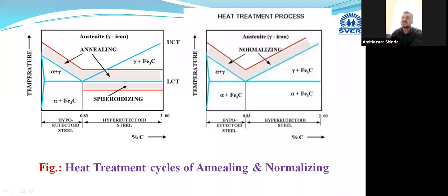And at this higher temperature zone, whichever grains of austenite are there will become coarse. Its size will become larger and larger, and whichever martensite we get at room temperature will be very brittle in nature. Hence, for conducting hardening, we are not heating above ACM for hypereutectoid steels. We use the temperature zone above A3 for hypoeutectoid and above A1 for hypereutectoid steels.